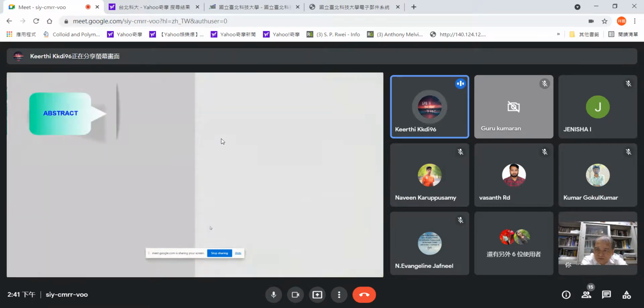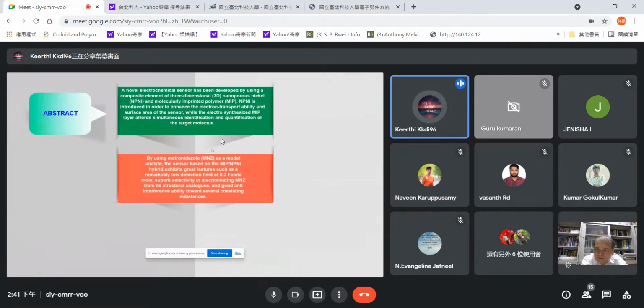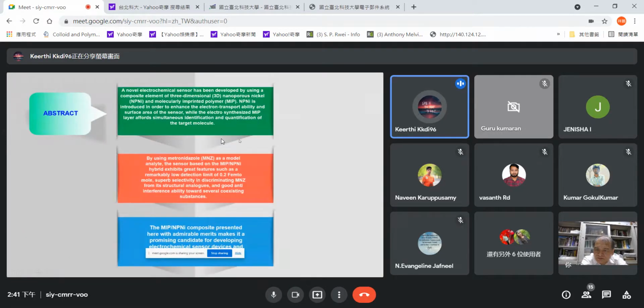Abstract of the paper. A novel electrochemical sensor has been developed using the composite of three-dimensional nanoporous nickel and molecularly imprinted polymer. The nanoporous nickel is introduced in order to increase the electron transport ability and the surface area of the sensor, while the electrosynthesized molecularly imprinted polymer layer enables identification and quantification of the target molecule.